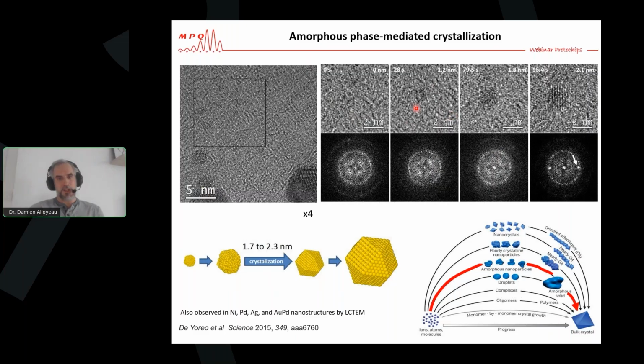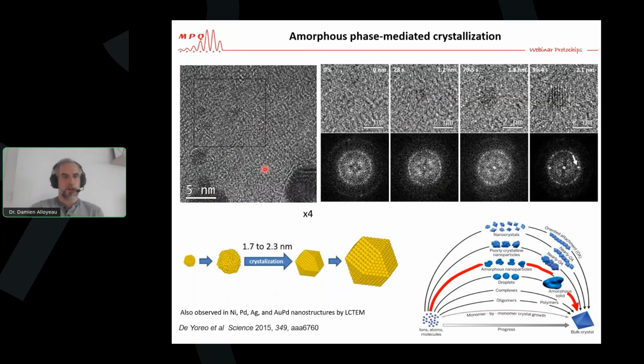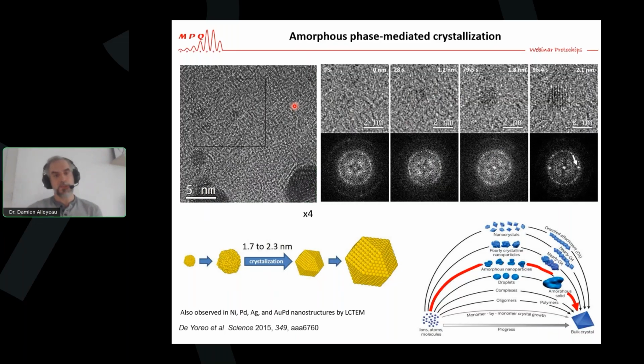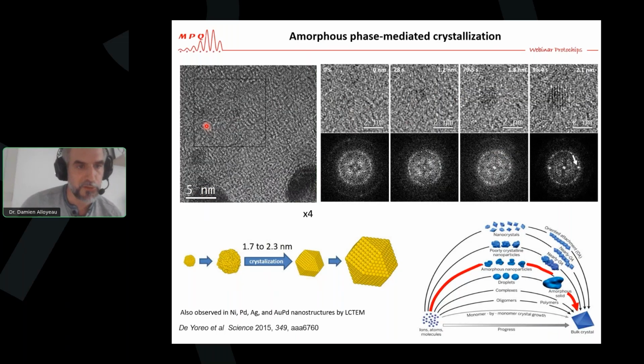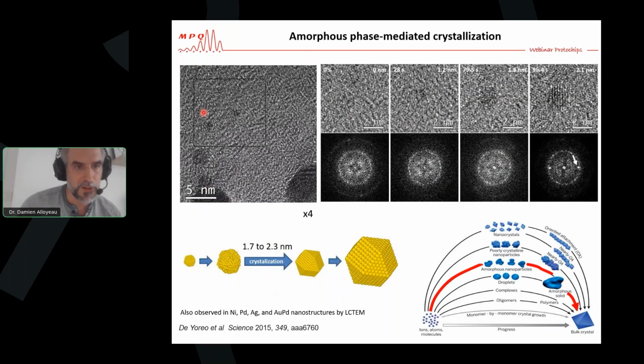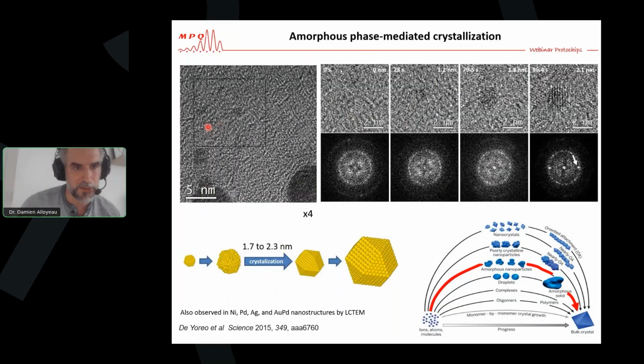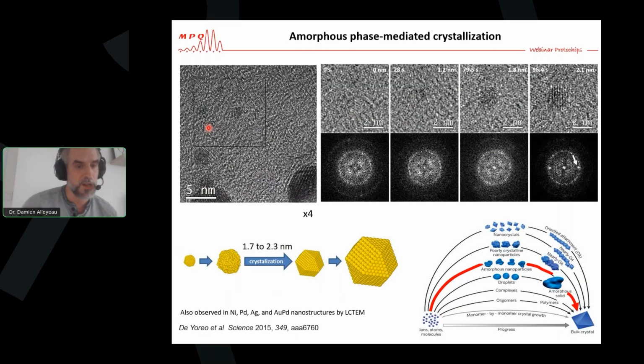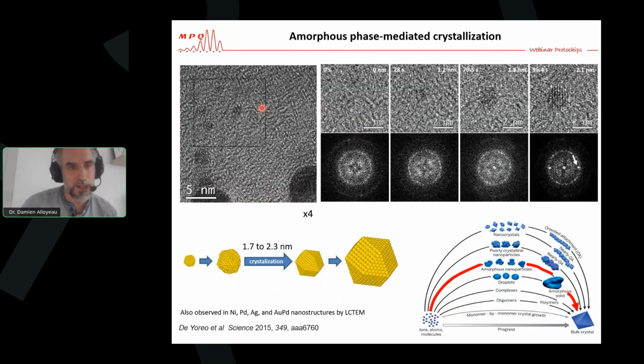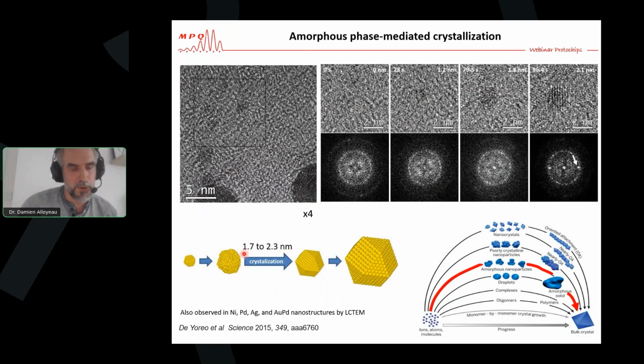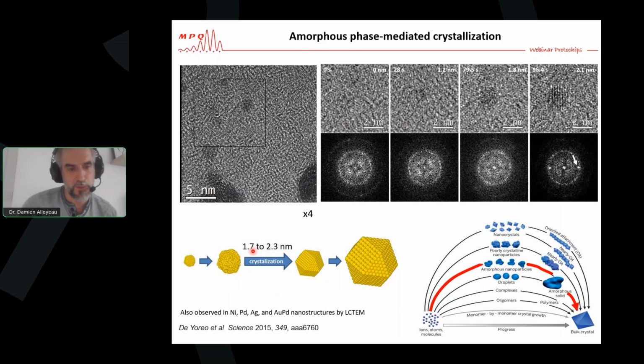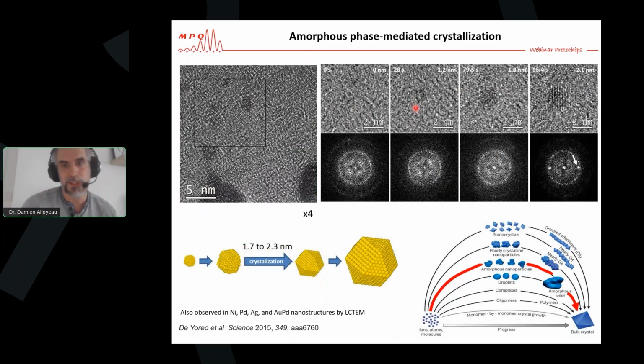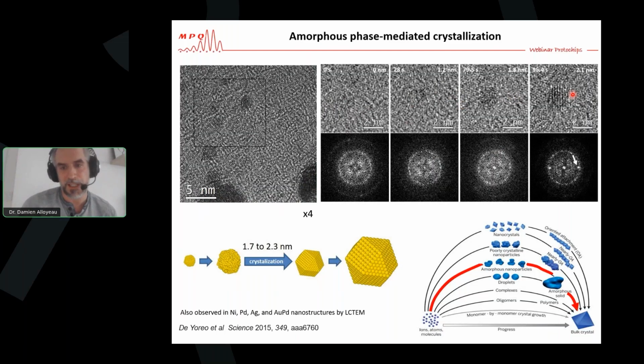And here you observe the full nucleation mechanism of a nanostructure. Occasionally you may have some nucleation mechanisms that occur, and here you observe 4 little amorphous nanoparticles. They are amorphous because they are below 1.7 nanometer, and when they reach a size between 1.7 and 2.3 nanometer, you systematically have the crystallization.